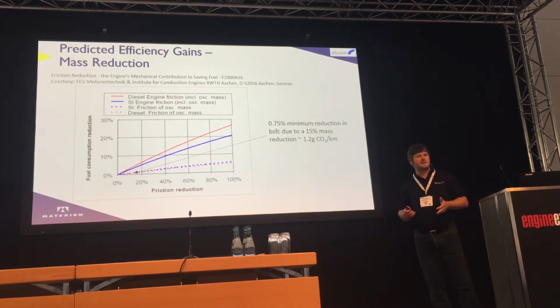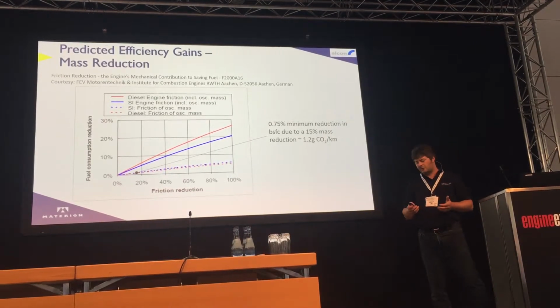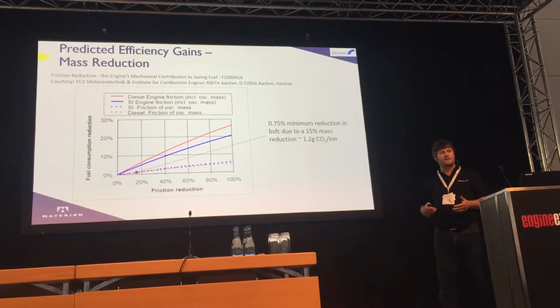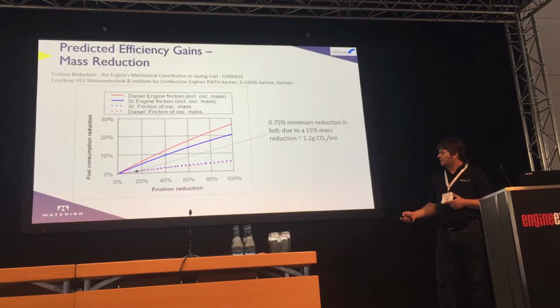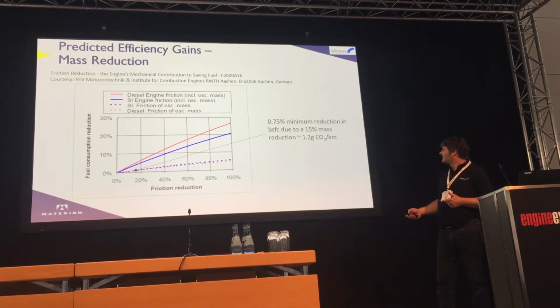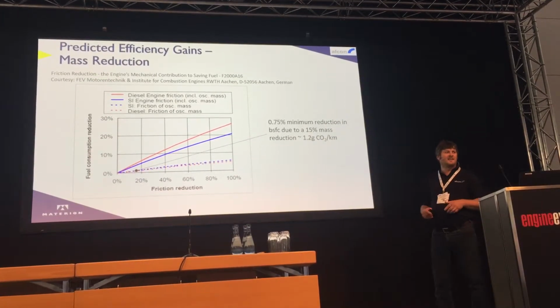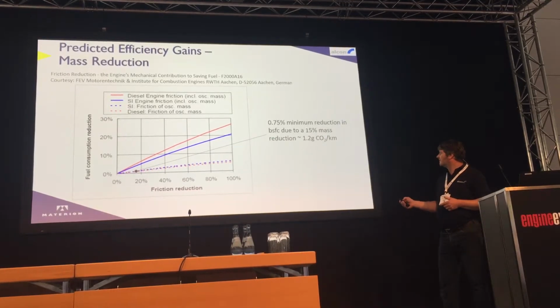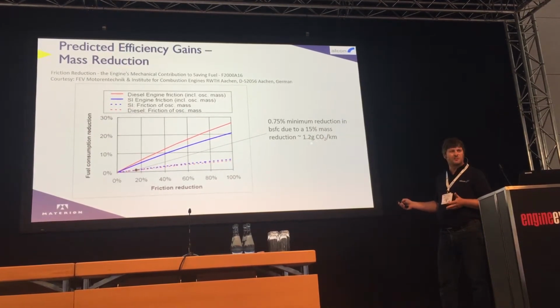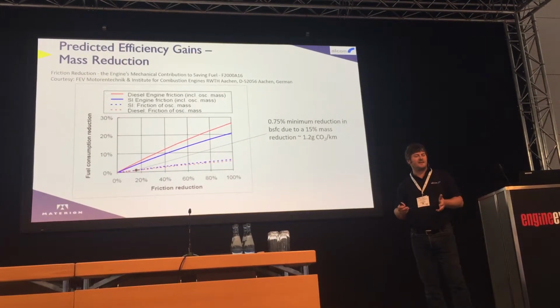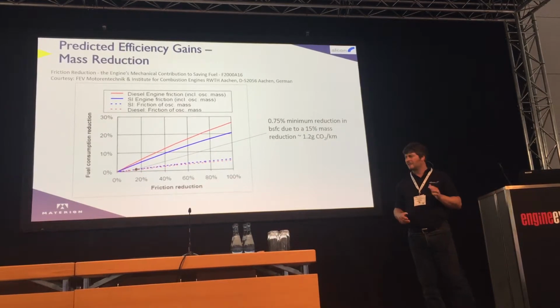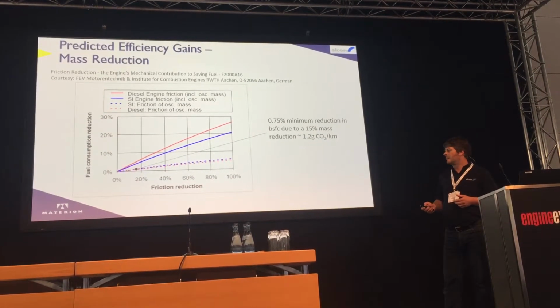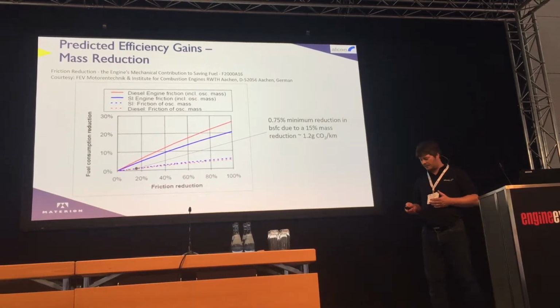In terms of reducing the reciprocating mass of the piston, it's always a difficult one to predict its effects in terms of friction. FEV carried out a study on lots and lots of engines over the past decade or so, and reducing reciprocating mass, this is the effect of a percentage reduction in friction, what that means in terms of a fuel consumption saving. So where we've saved about 15% mass, there's potentially a reduction in CO2 of about 1.2 grams of CO2 per kilometre. It's very much dependent upon the engine, whether you've got an offset crankshaft, offset pin, but it's only indicative, but the bottom line being that a saving in reciprocating mass tends to be an improvement in friction.